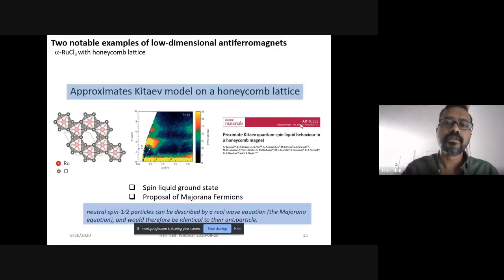Another very important material has, of course, a honeycomb lattice. It's formed by ruthenium, a transition metal, which forms a honeycomb. If you look at the extreme left crystal structure diagram, you can see a honeycomb, and the red atoms are ruthenium. So if you look at the red spheres, you would see a honeycomb. The middle diagram is a measurement of energy on the y-axis and reciprocal lattice spacing on the x-axis. It is nothing but a map of energy transferred by neutrons to the sample when they hit it. So it's a color map at 5 Kelvin showing what happens if you bombard the sample with neutrons and transfer energy to the spins.